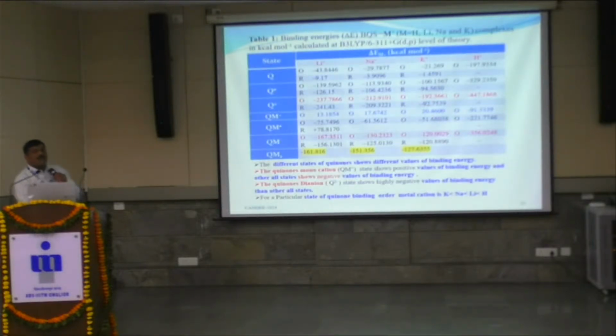These calculated values for various lithium, sodium, and potassium cations are as shown in the table, and the different oxidation and reduction states of the quinones show different values of binding energy. But the quinone with monocation, QM+ state, shows a positive value of binding energy, and all other states show negative values. These values are in front of the oxygen, and R represents the binding energy over the ring of the quinones. Then the quinone dianion state also shows highly negative values of binding energy compared to all other states. For any particular state of the quinone, the binding energy with the cations goes on increasing in the direction of lithium to potassium,